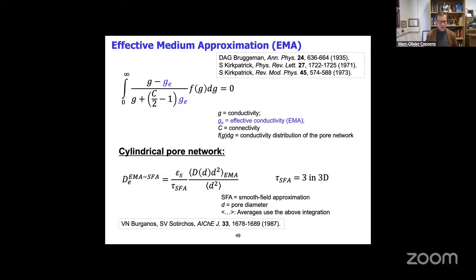Okay, and so a theory I want to highlight in this context is the effective medium approximation, or EMA theory, which was introduced by Bruggeman already in the 1930s and then generalized to pore networks by Scott Kirkpatrick in the 1970s. And so what's very elegant in this is that you have these pore networks or networks of resistors or conductors with a certain conductivity G. And so you assume that you keep the whole topology of that network, but you replace all these conductivities by a single value, GE, and you call that the effective conductivity. And if you do that, you can solve this equation here.